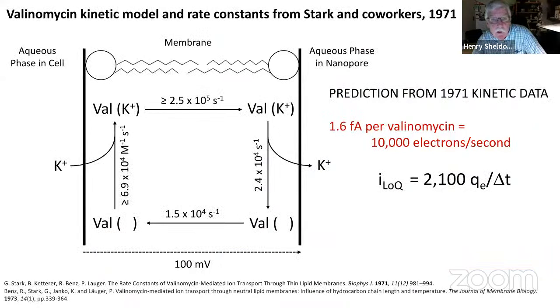The reason we're working with this is because back in the 70s, there was a group, I believe from Germany, the lead PI was someone named Stark, who did a lot of kinetic measurements on transport of potassium by valinomycin in a lipid bilayer, applying 100 millivolts across the surface. These were measurements done with macroscopic bilayers, and by macroscopic, I mean a circular bilayer with a radius of 50 microns or 100 microns. They did a lot of classical experiments, pulse measurements, and different types of measurements to work out the rate constants for these 4 steps here.